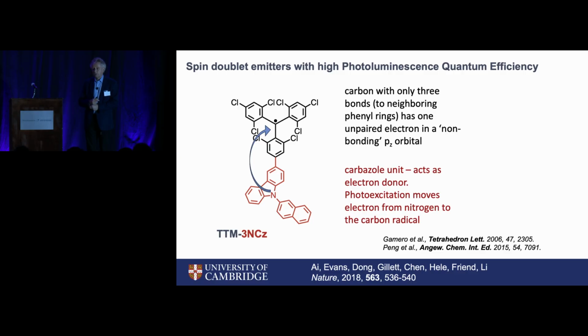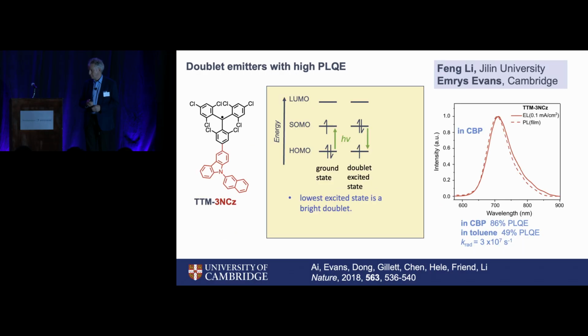What happens with this carbazole system is that the optical transition is transferring an electron from the lone pair on the nitrogen, a non-bonding level, to the singly occupied methylene carbon, the radical, that's the black dot at the top. That charge transfer transition is relatively allowed, and it gives a very nice deep red emission. Here's the same molecule on the left. On the right is its luminescence spectrum. You see it luminesces with a peak just beyond 700 nanometers, so it's deep red. Rather surprisingly, most molecular materials are very good in the blue and the green as fluorescent materials, as phosphors, but they're lousy by the time you get to the infrared, for reasons I'll touch on.